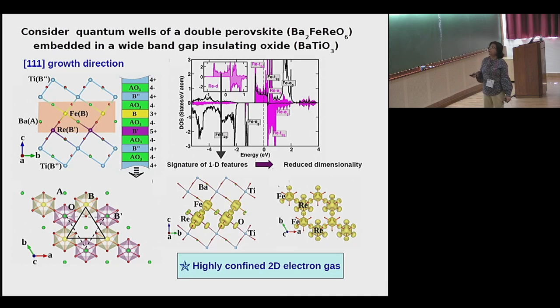If you compute its density of states, it's pretty similar to that of the bulk, except that there is a significant narrowing of the bandwidth compared to the bulk density of states, and also there are Van Hove-like features at the band edges, which signal dimensional confinement by making such a quantum well structure. That is also seen in the plot of the conduction electron density, which is strongly localized only at the iron and rhenium sublattice of this double perovskite. So by these we generated a highly confined half metallic 2D electron gas.